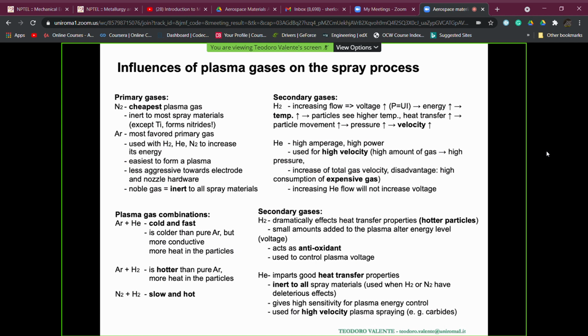For the primary gas, the nitrogen is the cheapest plasma gas, and it is widely used because it is inert, that is not able to give rise to chemical reaction to most spraying materials. One material which cannot be sprayed with nitrogen is titanium, because titanium has a high affinity with nitrogen, and after recombination in the plume, there could be a reaction between titanium and nitrogen to form nitrides.